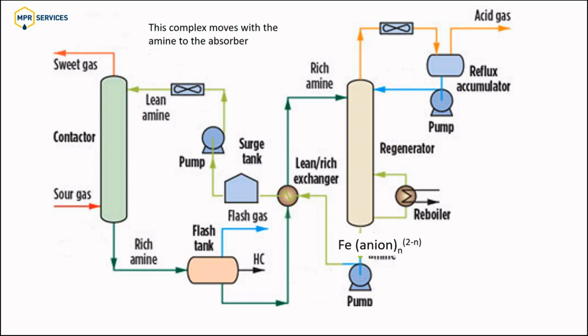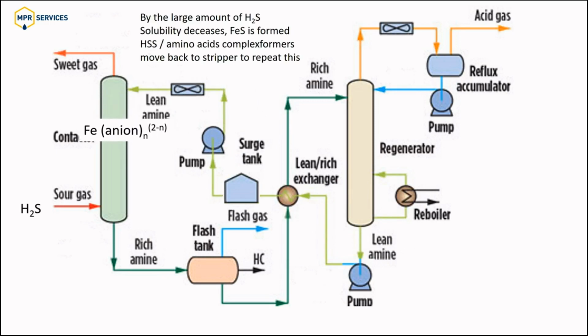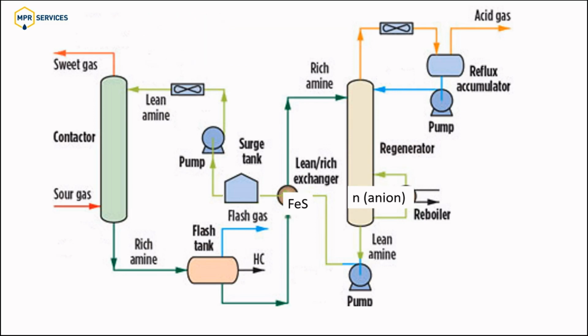This chelating mechanism is shown on this schematic. Iron from the protective layer, or even transition metals like chromium and nickel from stainless steel, form a complex with the heat stable salt anions or amino acids. This typically happens in the lower part of the regenerator, in the reboiler also, and in the hot lean amine piping.